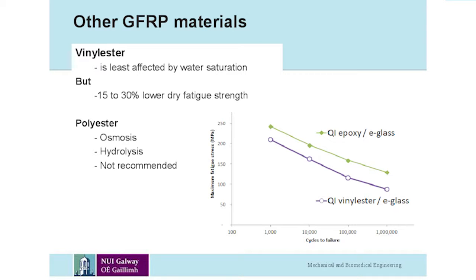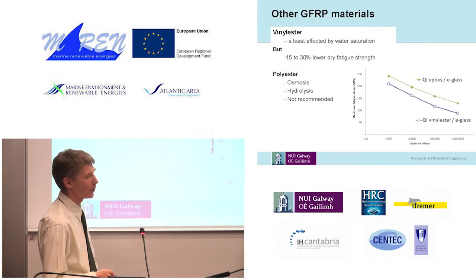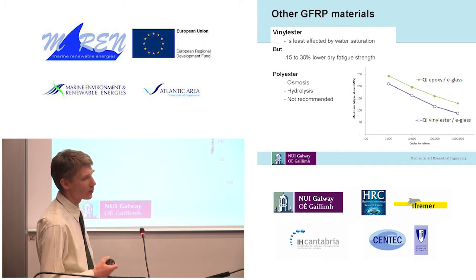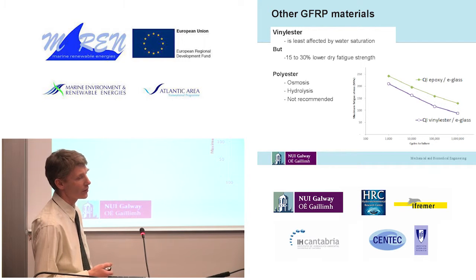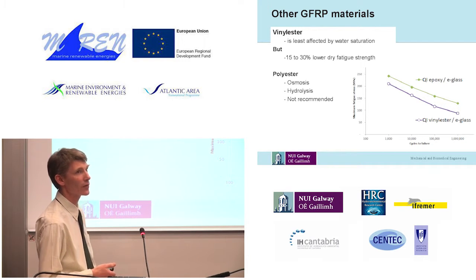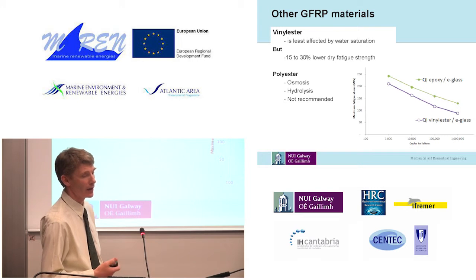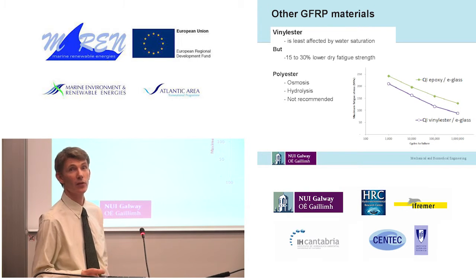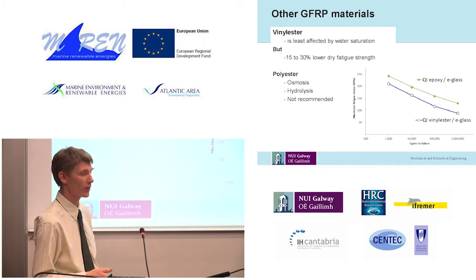Now, there are some other GFRP materials that are also useful. In particular, vinyl ester is the least affected by water saturation, but it does have a lower fatigue strength to start off with than epoxy. So you're going to lose maybe 15 to 30% of your fatigue strength by going to vinyl ester. Now, it's a little bit cheaper than epoxy, so there may be a trade-off there. In some situations, it may be good to use.